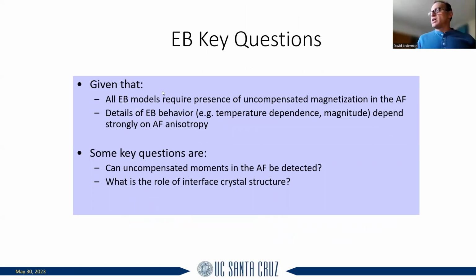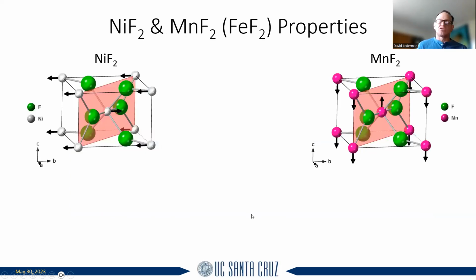So basically, we had these questions, which was, all of these exchange bias models require the presence of uncompensated magnetization at the interface between the ferromagnet and the antiferromagnet, and the fact that the anisotropy of the antiferromagnet matters a lot. The questions were, can we detect these uncompensated moments in the antiferromagnet, first of all, because you need to have some uncompensated moments in order to have a net exchange. And what is the role of the interface crystal structure? Okay, so those are some questions that we decided to address.